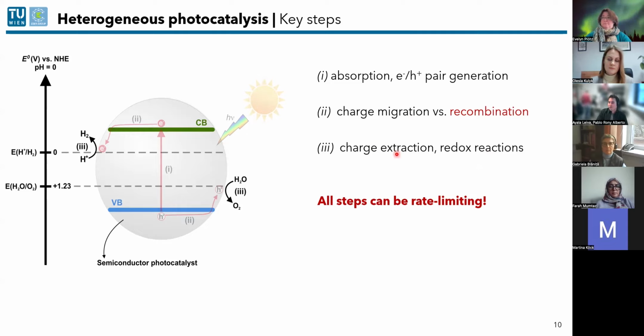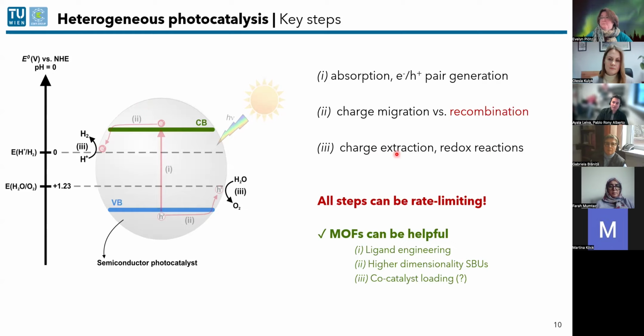And now we want to see how MOFs could help us tackle some of these steps or limitations. So for one, for the light absorption, we could do some ligand engineering. For step two, which is also pretty challenging, we could investigate higher dimensionality SBUs, for example. And for step three, we could add a co-catalyst, which helps us extract the charges better. Usually people use platinum nanoparticles. However, in MOFs, there's a great opportunity if we can design secondary building units that already have a co-catalyst in them, then we might have also better results. But for today's talk, I would like to focus mainly on this charge migration and charge extraction. So step 2 and 3.